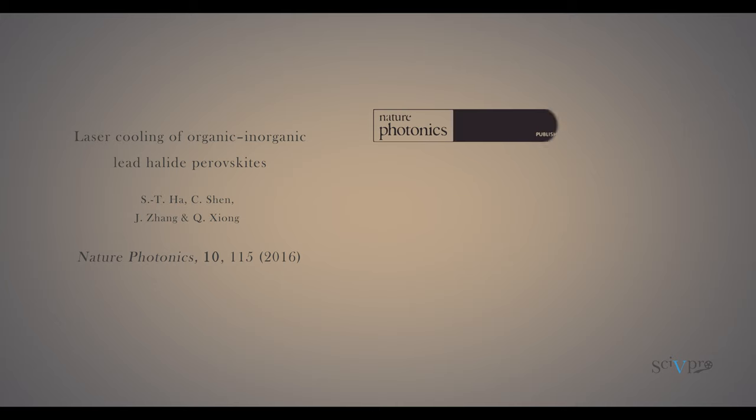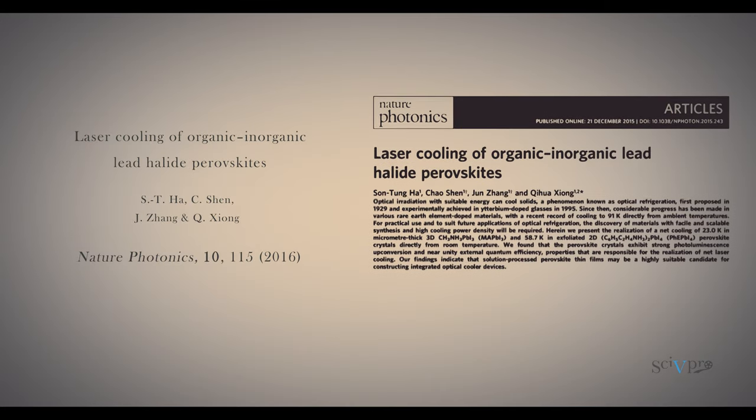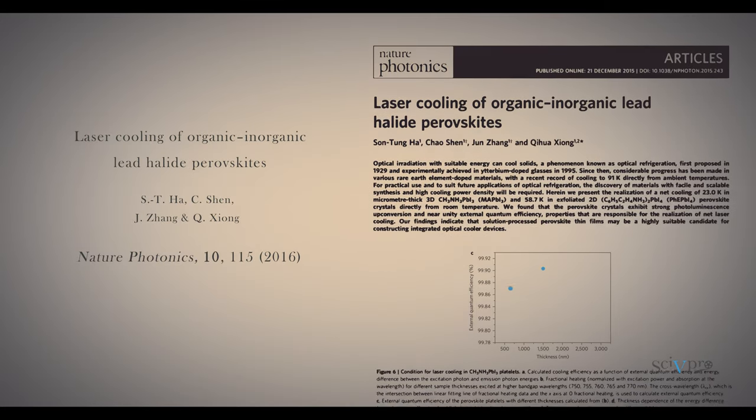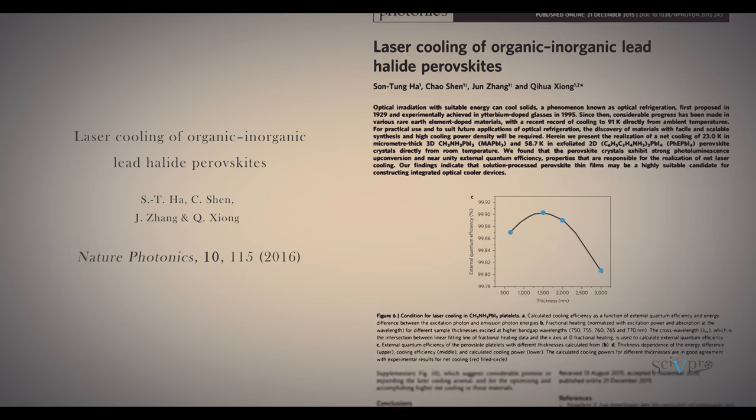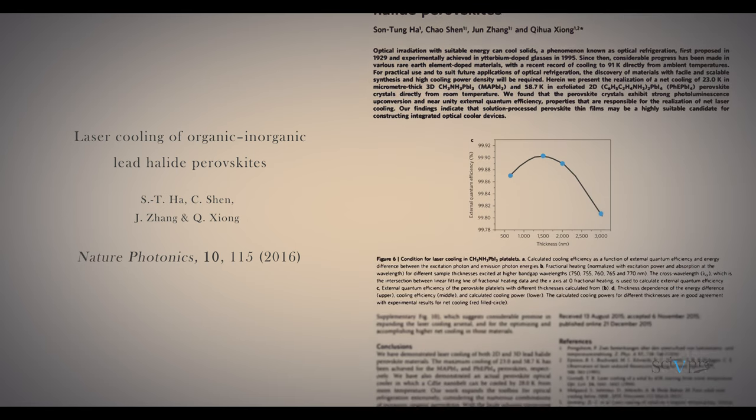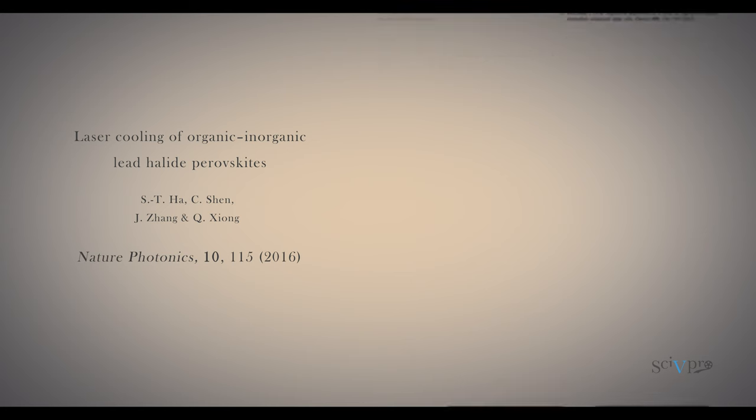I think the key is the ratio of the radiative recombination processes against everything else going on which can quench the luminescence, and it is again surprising that the non-radiative channels are relatively unimportant. Also because this paper that came on Nature Photonics a few years ago about laser cooling showed something in the order of 99.8% external luminescence efficiency, and that's really extraordinary.